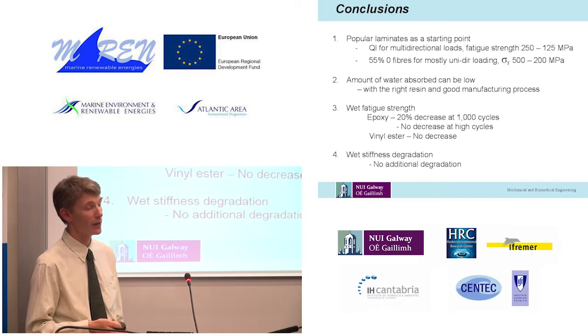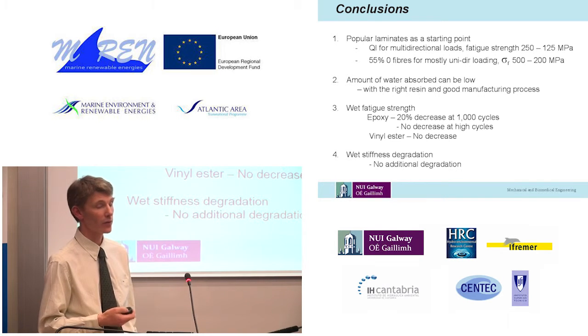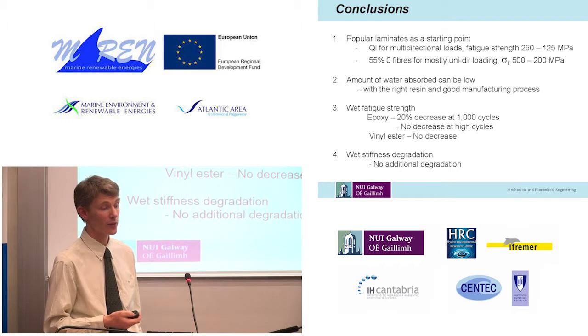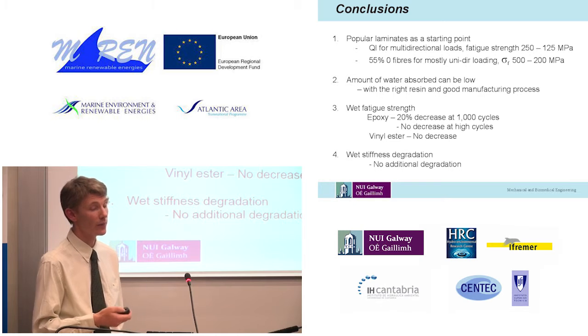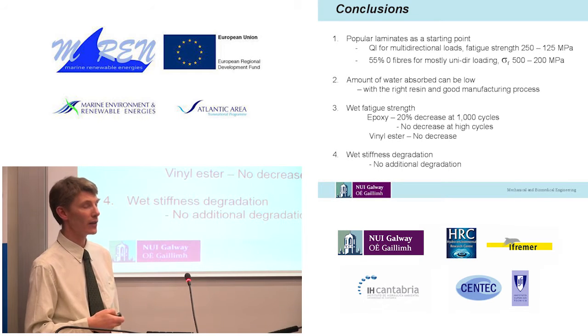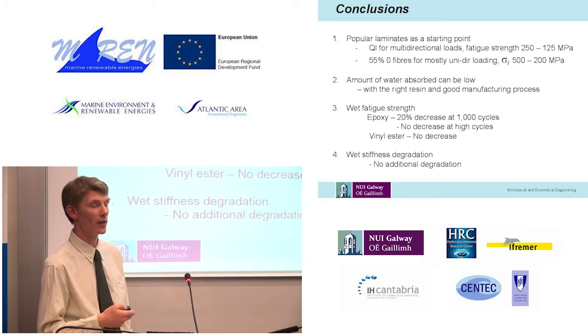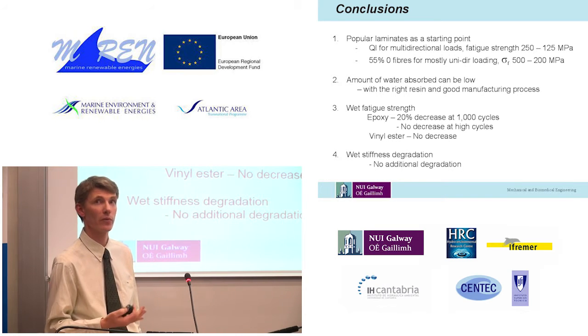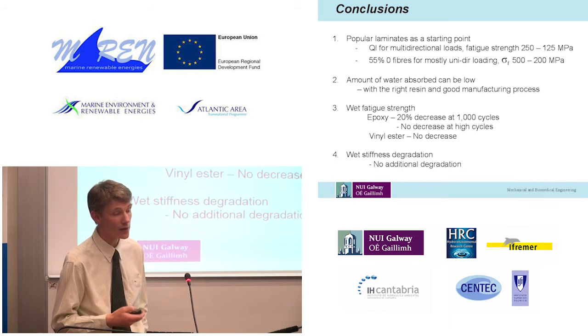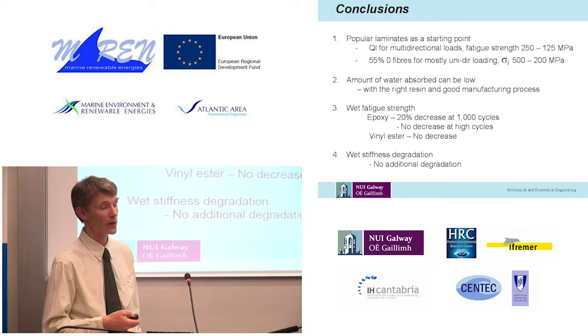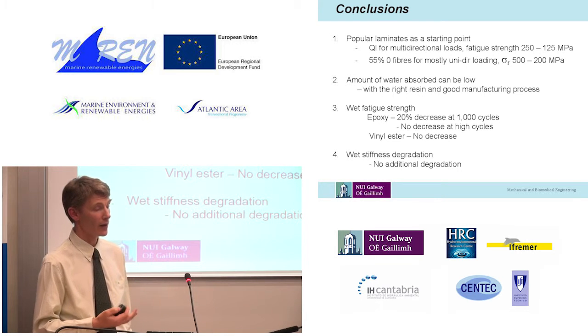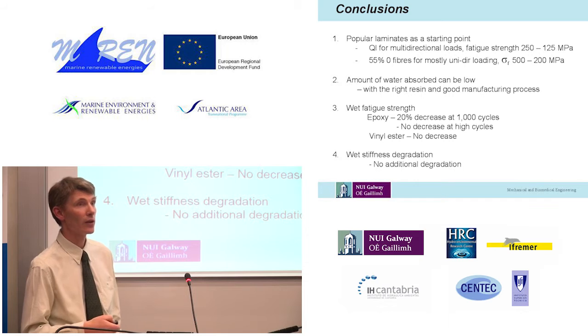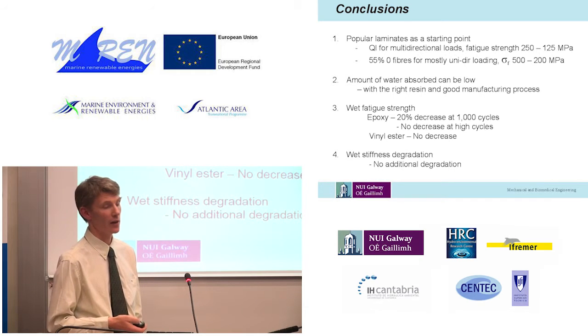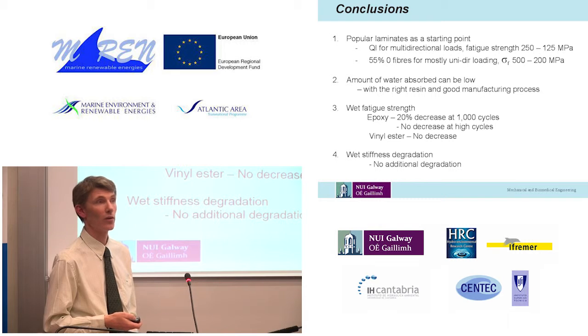In terms of the wet fatigue strength, I've shown that epoxy has about a 20% decrease at 1,000 cycles to failure, and at some point in the high cycles, there's no difference between the wet and dry material. And for the testing I've done, certainly the vinyl ester seemed to show no decrease due to saturation. And then the other thing I've shown is that there's no additional stiffness degradation due to water immersion.